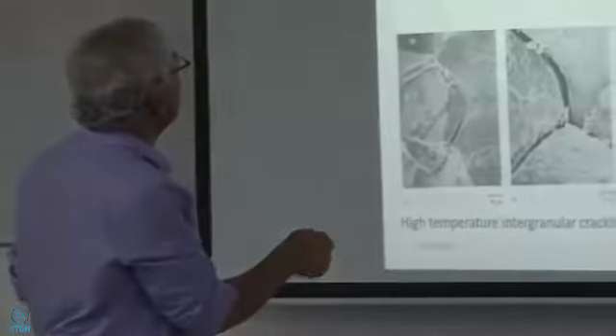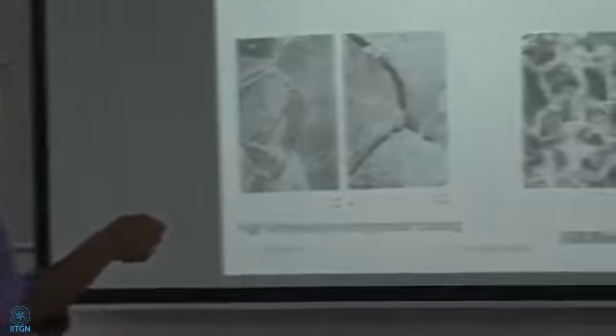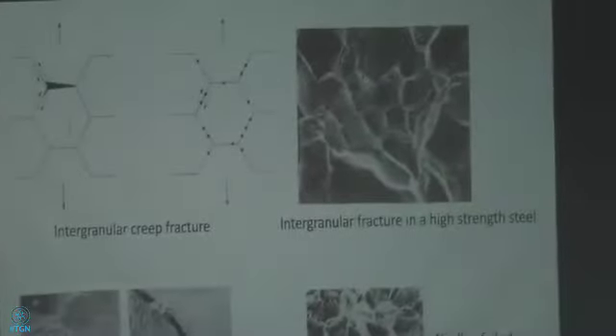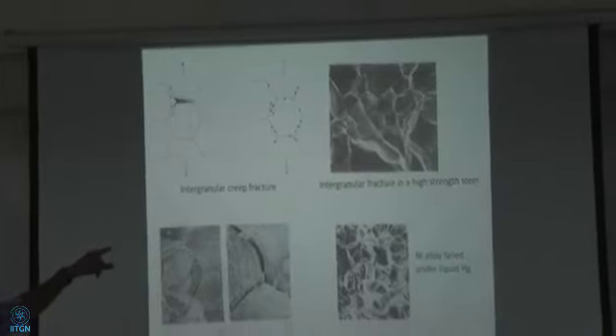So if it gets too hot, for instance, the pipe will start to sag because of the temperature. That means it's creeping. So it happens very commonly in the chemical plants. One of the most common failures in chemical plants is intergranular fracture by creep. It's a common fracture mechanism in creep.